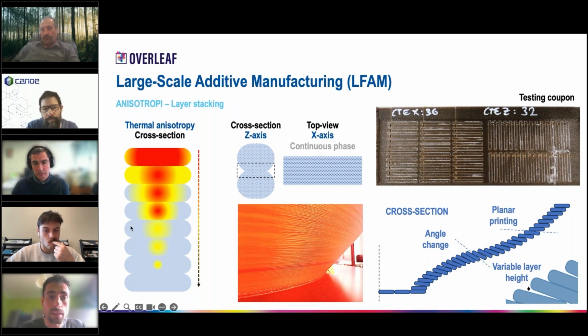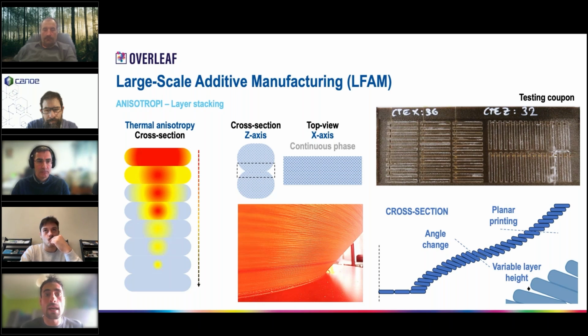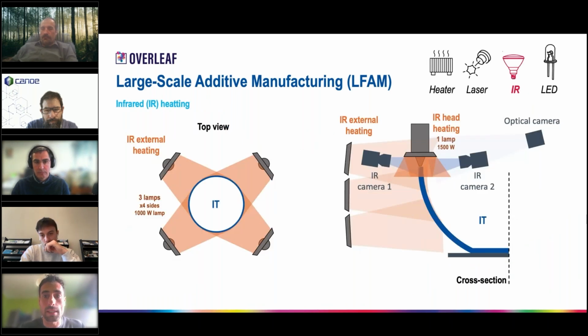Besides, on top we are printing at very high temperatures because we are printing melted materials, but at the bottom of the tank, it will be completely cold. So this is generating an extra problematic. What do we do for that? As we'll see later, we are making testing coupons to understand the behavior in both directions, but from the manufacturing point of view, we have to be able to homogenize and make our materials as isotropic as possible.